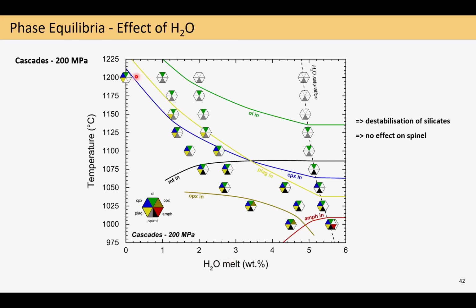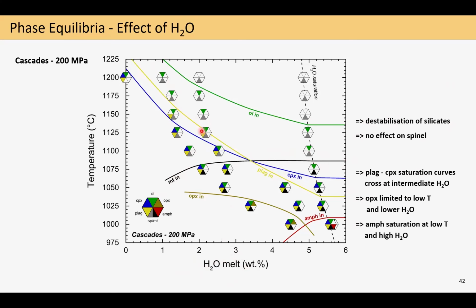And overall, we can see here a general destabilizing effect of water on silicates, while apparently spinel stability, here exemplified with magnetite, is not affected by the meltwater content. And if you look now in more detail, we can see that the plagioclase and clinopyroxene saturation curves cross over here, roughly at intermediate water contents, that pyroxene stability is limited to lower temperatures and lower water, and that amphibole saturation was only reached at high water and low temperatures.